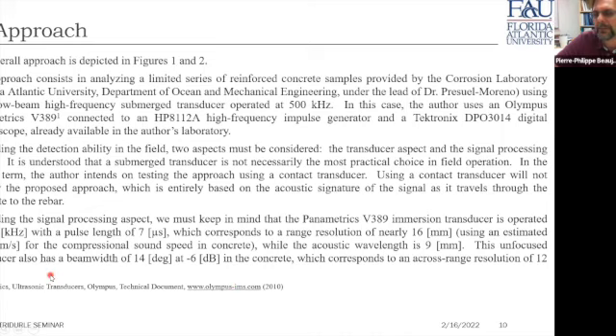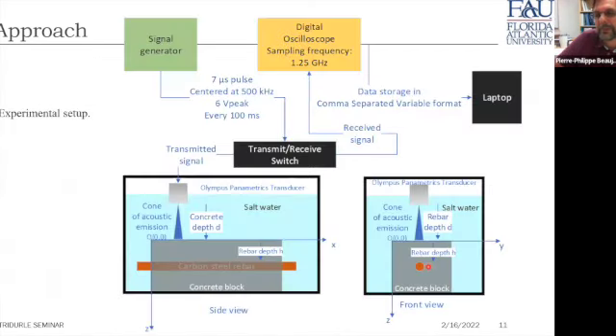So what does this mean in plain words? In plain words, it means that if we were to use this transducer solely for the purpose of imagery to find a concrete flaw, this transducer would cover a fairly wide area over the rebar and would not be able to create an image with a resolution of less than approximately 9 to 12 millimeter, which corresponds to a significant crack already. However, the model itself can actually lead to earlier detection of the crack. So is the intent. Now, here's the experimental setup.